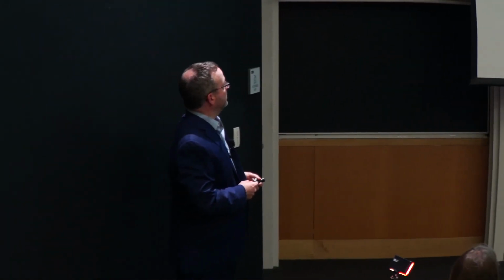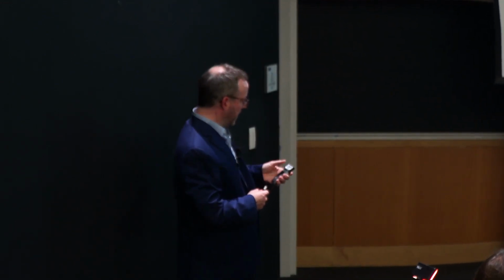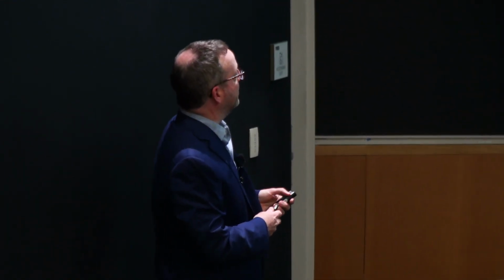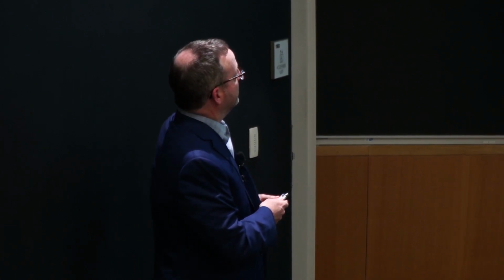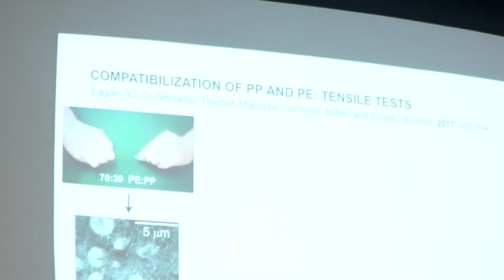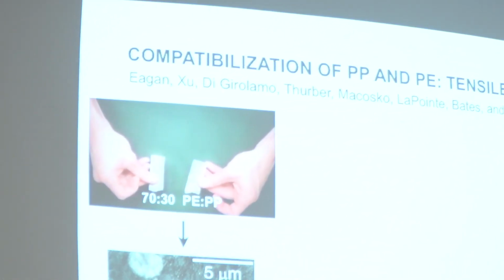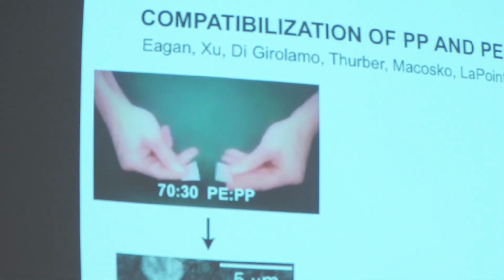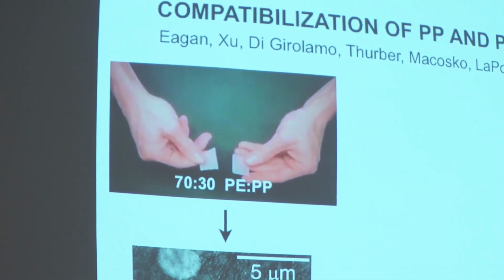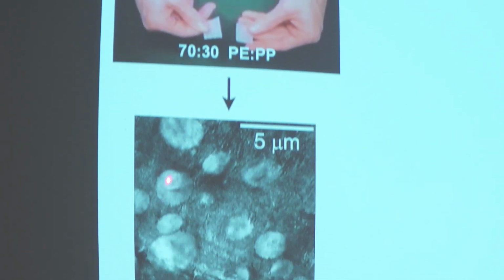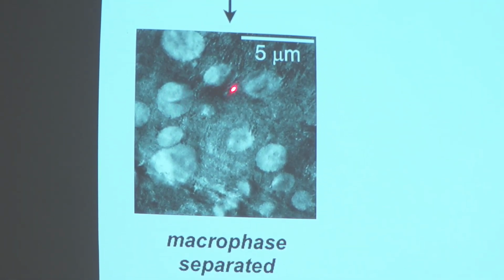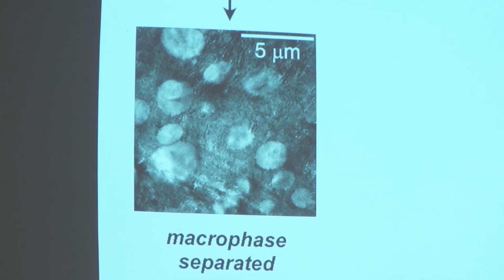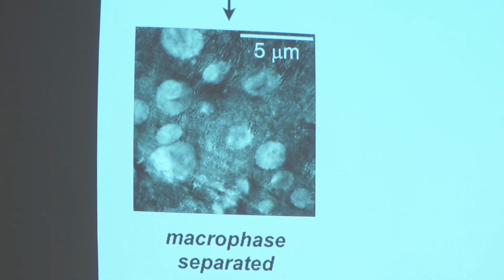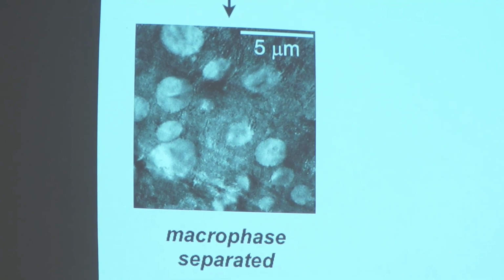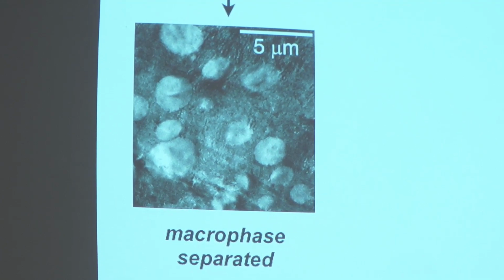Okay, so the question is, do they work? And I'm going to show you one slide here and that kind of summarizes the work that we've done in this area. This is the little bar that I just showed you. If you just take polypropylene and polyethylene and try to melt them together, it's really crumbly, arguably having greatly inferior properties to the pure polymers. And the reason, again, for that is this macrophase separation. That's polypropylene. And the interface between the polyethylene matrix is very weak. And so think of this almost as like you're perforating your polymer and giving it the ability to kind of tear down through these surfaces.